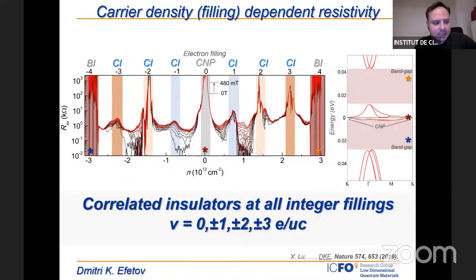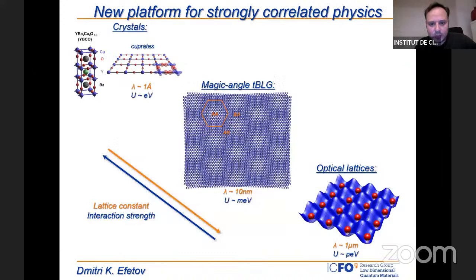Okay, so those are the correlated insulators, but I also want to put this in perspective in terms of other correlated insulating systems which have been observed before. Of course, Mott insulators were observed in normal crystals, for example in the cuprates. Because everything happens in the crystal lattice itself, the lattice spacing is much smaller, on the order of angstroms, and therefore the Coulomb energies are much higher, on the order of eV.